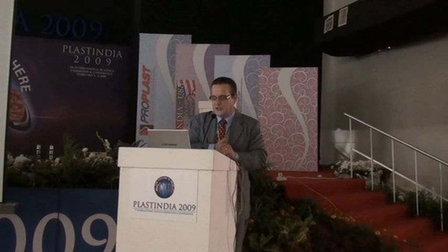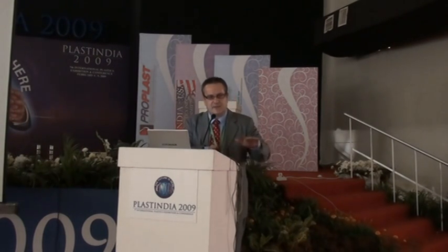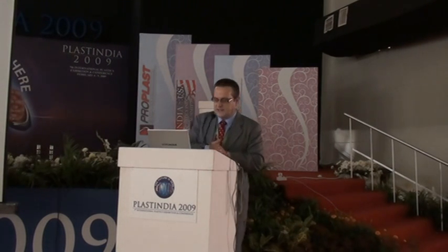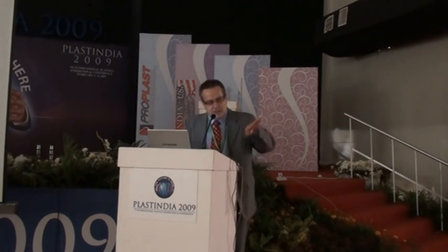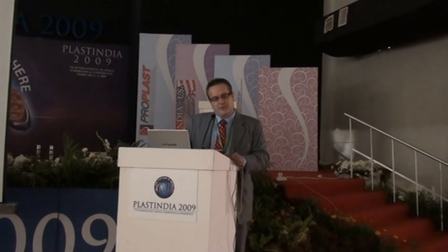We can eliminate silver streaks, which are formed when we have a structural foam material. So if you add a blowing agent to foam the material, normally you have to sand the moulding down and then paint it. Well, again, we can achieve a Class A surface finish without the need for painting. We can achieve excellent replication of the mould surface. So if we have a textured surface, we can pick up that texture much better. Again, because we're retarding the freezing of the polymer to allow the material to go into the peaks and troughs of the grain surface. We have improved optical properties, less birefringence and a more uniform refractive index when we're producing lenses.